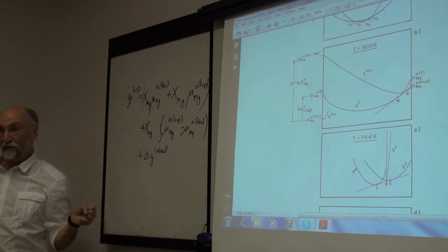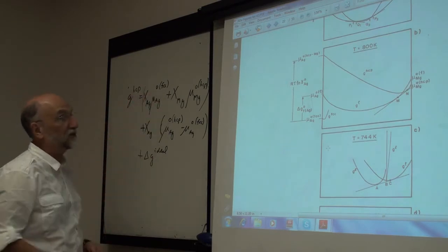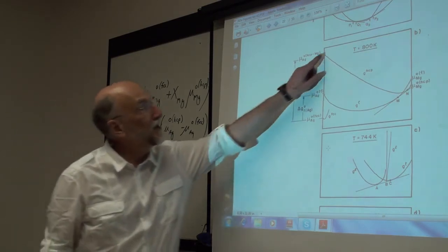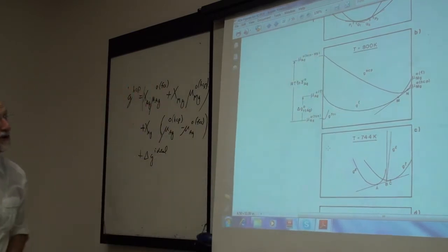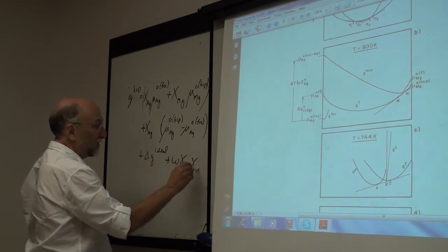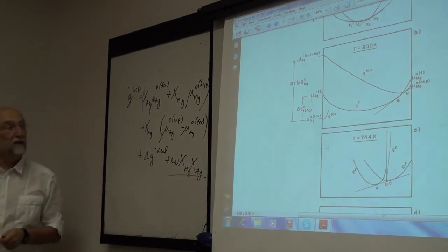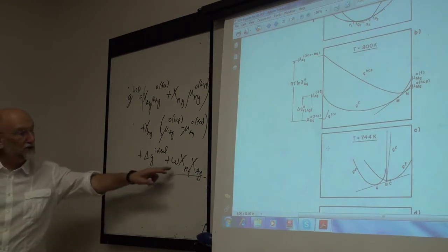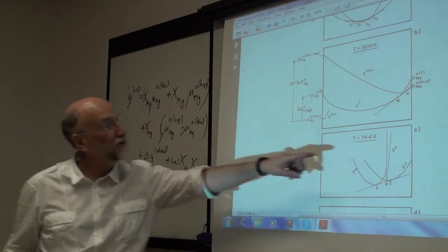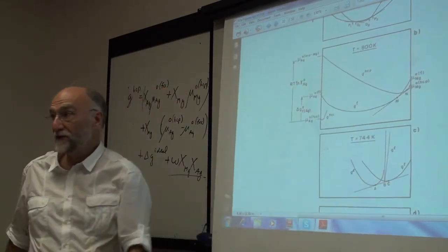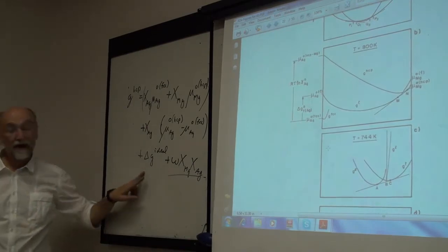Okay, we went through the whole thing before. This is RT log gamma. Okay, you remember? Now we say, well then you can go a little bit further, and that's assuming your ideal Henrian solution. And I said, well then you could add a term here, omega x magnesium x silver, if you wanted to make it a regular Henrian solution. So this is, again, just with respect to these standard states, you just added a GXS term, x1 x2 times GXS, to that term. So this is just a regular solution term added on top of the...